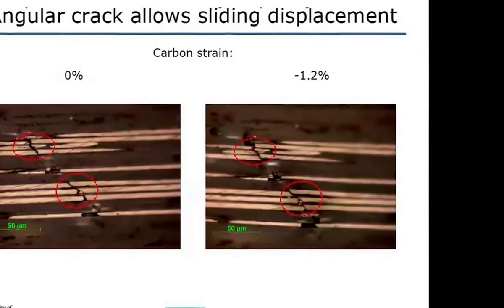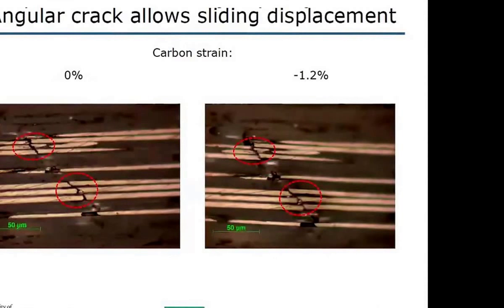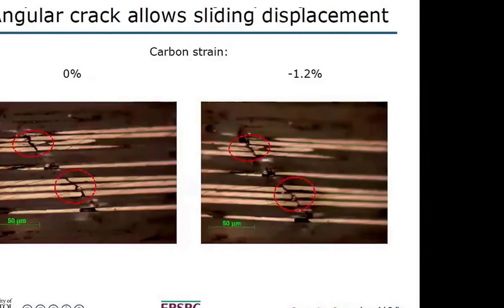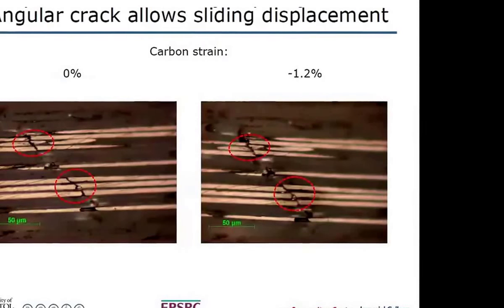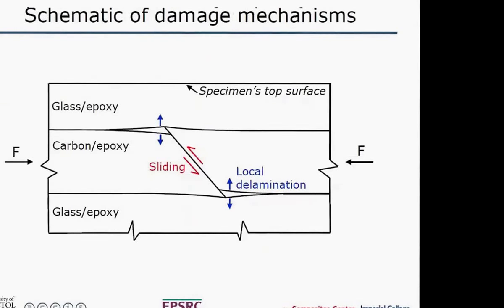If you look at this one here, particularly this lower fragment, over on the left-hand side you can see the orientation of the fibers. And if you look at this one here, you can see how it's moved upwards relative to this one. But also, because of that roughly 45-degree angle, it has moved in this direction as well. So you can see how that wedging action, as well as pushing out this way and producing a bit of delamination, enables a change in strain in the fiber direction to occur. So that's the mechanism by which this fragmentation behavior can occur.